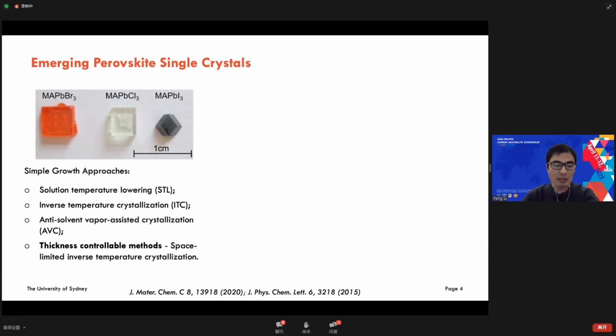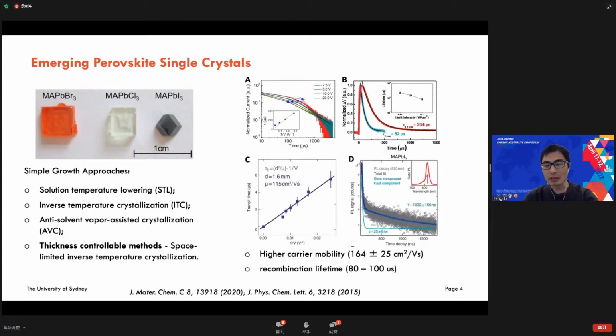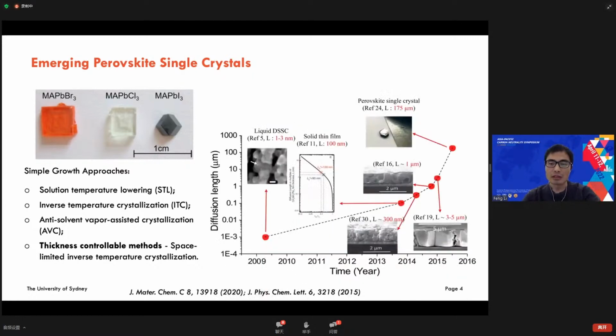We can use the space-limited method to reduce the thickness of the single crystal, and we can fabricate the particular device. They have advanced, more promising properties. They have very good charge transfer properties, with very high carrier mobility and a very long recombination lifetime.